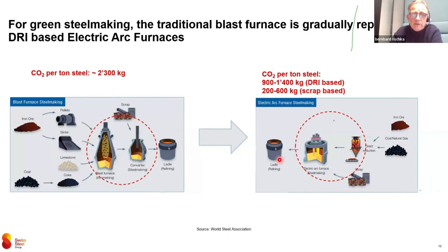The picture looks different if you have an electric arc furnace being fed by scrap. But we will see later that scrap at the moment is insufficient in quantity. So we still need to feed our steel making cycle constantly by iron ore. And since you cannot melt iron ore in the furnace, we need the DRI plant, either by Midrex or by HYL, where you reduce the iron ore to an iron with a high metallization of 95%. And to do so, you need to reduce it with natural gas.